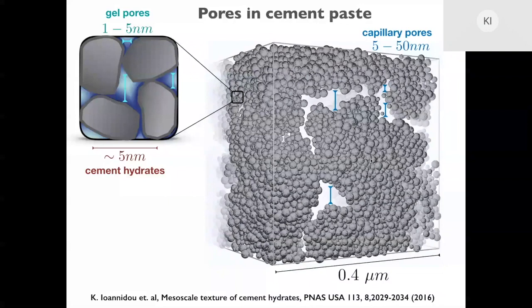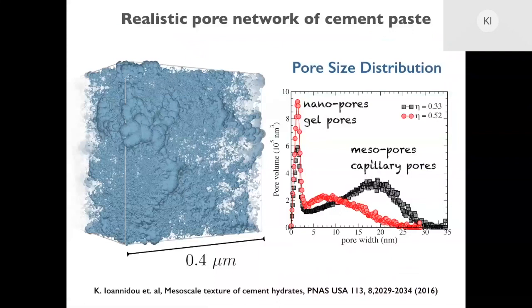So what I've just shown you here is the cement grains in gray. And if we visualize the opposite, the pore space, you see it here in blue. This is a space that will be filled with water, and it will be filled with water at a different degree of saturation, depending on the type of simulation we do. And also I want to show you the pore size distribution that we get from simulations, and we have validated from experiments that it has exactly the two features that we find in experiments, which is this first peak of gel pores, and then this very broad distribution of capillary pore sizes.